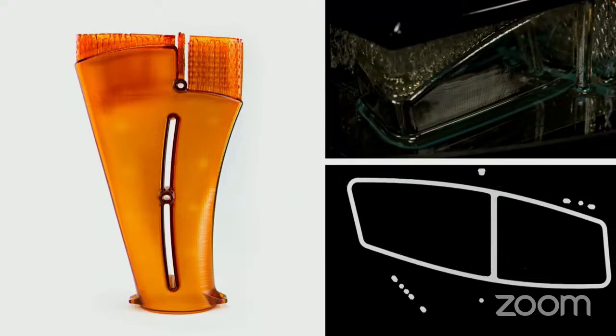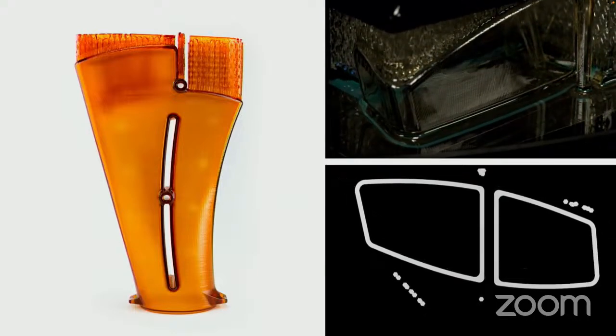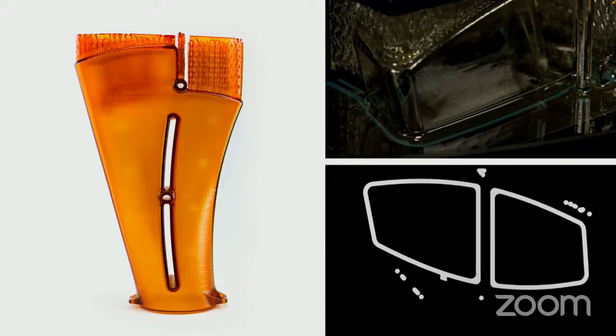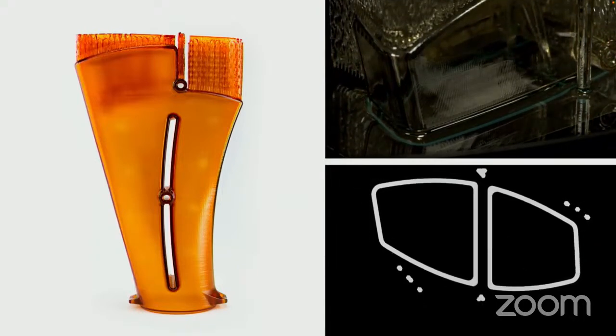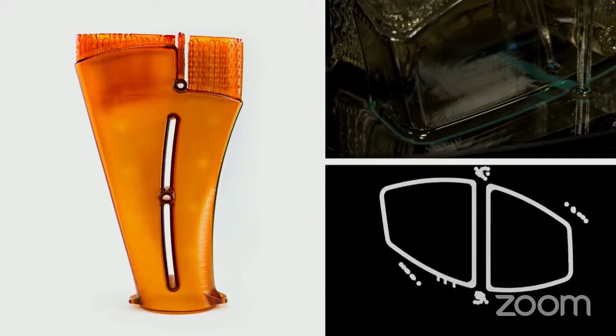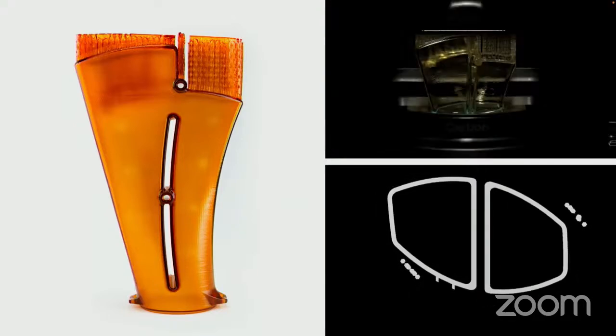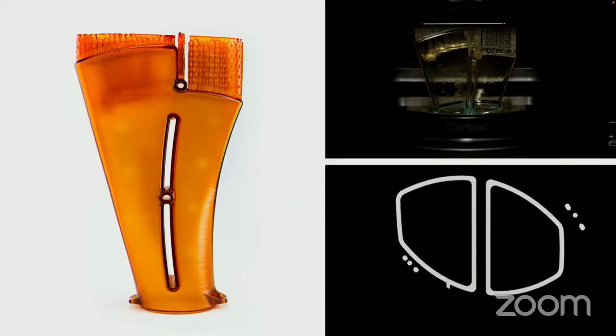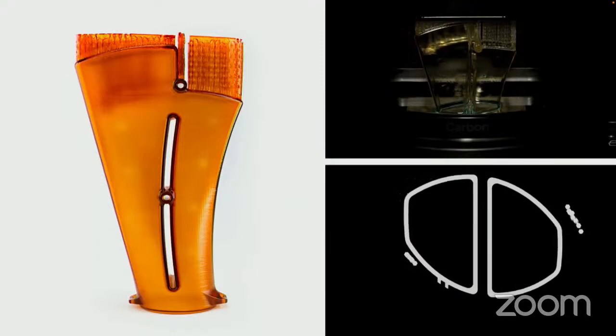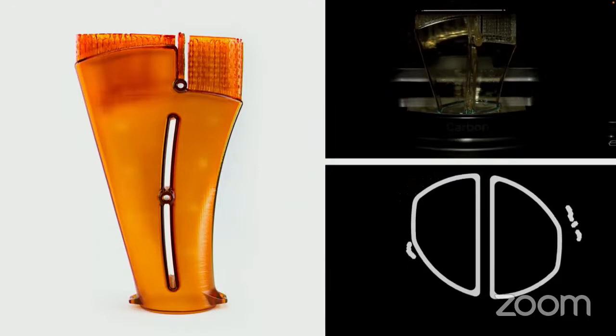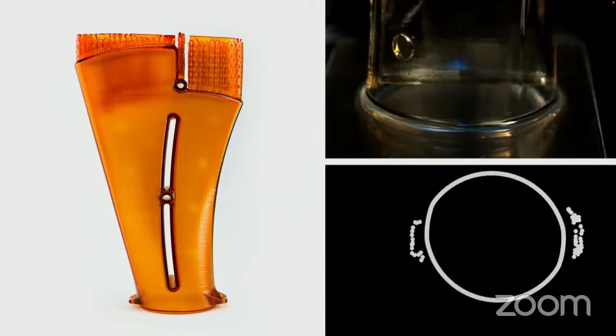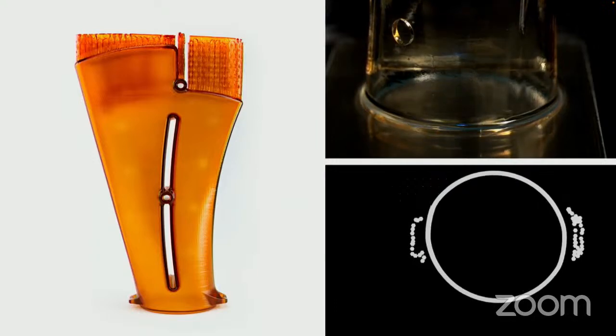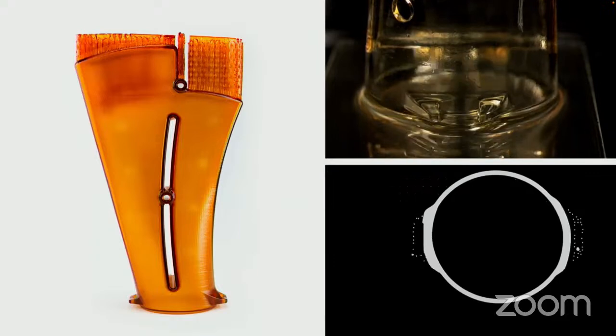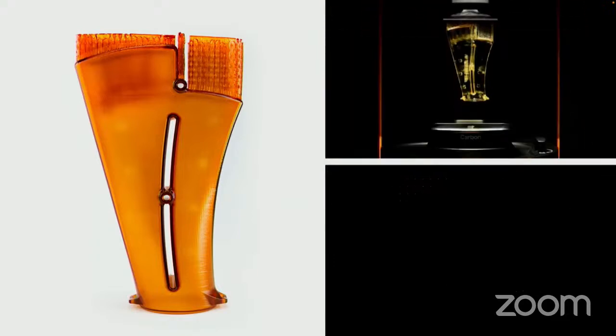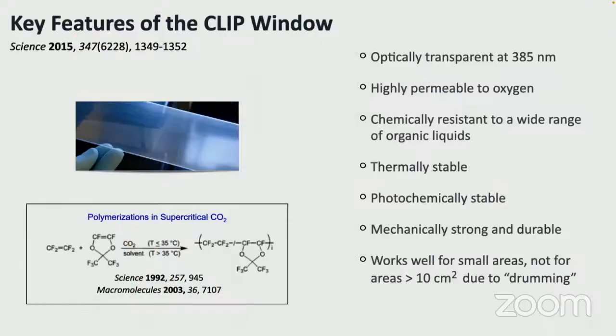The resin will bond to this metal platform, adhesively bond to it, but it doesn't bond to the window because of the oxygen replenishment, and there's a gap between the part and the window. And as you pull the part up, there's a suction force that draws resin in underneath it. And as this platform moves, and this is an accelerated video, this is 100 to 1,000 times faster than traditional 3D printing running in this manner. And because we're using this projection of light, we can basically make unmoldable things. And this breakthrough in speed allowed 3D printing to transition significantly to a manufacturing setting.